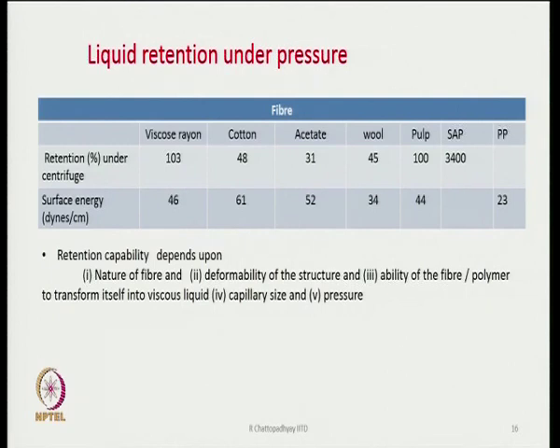Now, liquid retention under pressure, some data we could see, and they are all given here. Retention under centrifuge data could be seen, these values are stated here. And the surface energy of some of these fibers is also stated here. So, retention capability depends upon the nature of the fiber, and upon the deformability of the structure. How deformable is it, if it is non-woven? Does it get compressed easily by applying a little bit of pressure, or does it resist deformation? This will depend upon the bending rigidity of the fibers, and therefore on the coarseness of the fiber that is used.